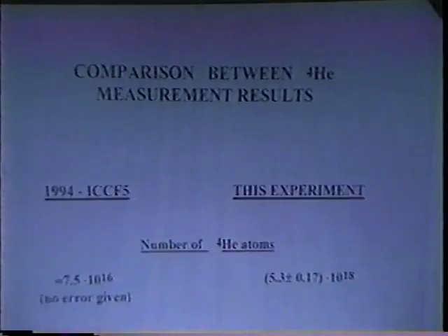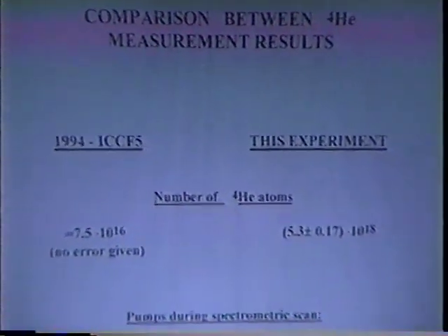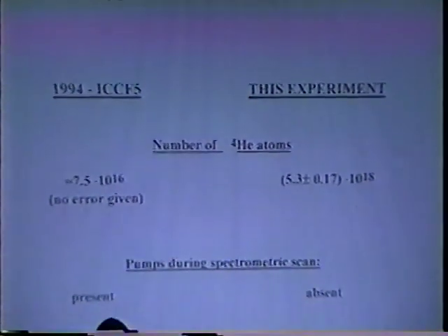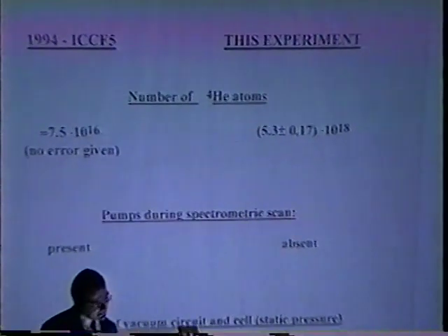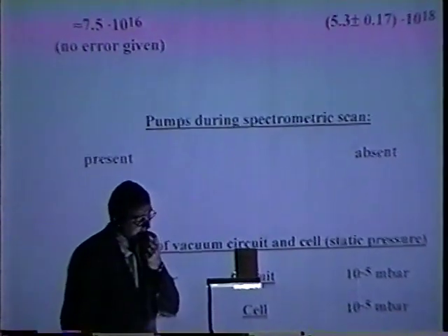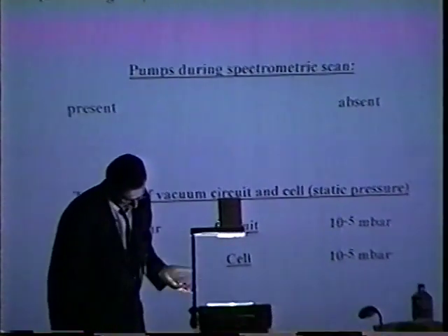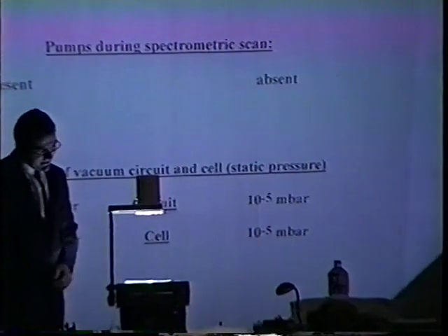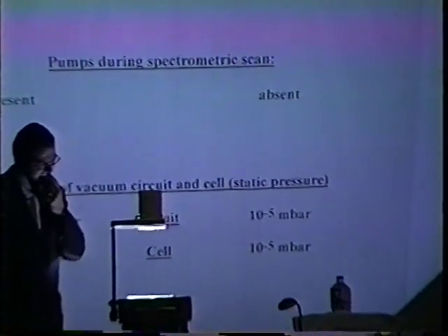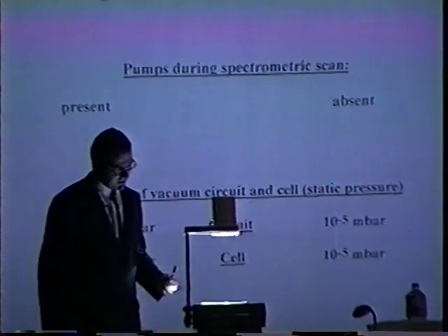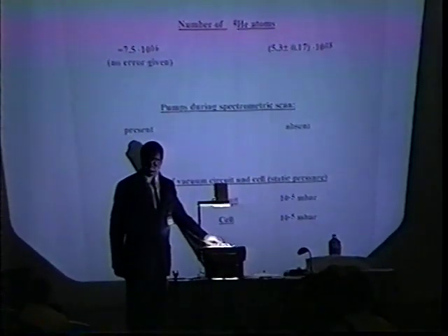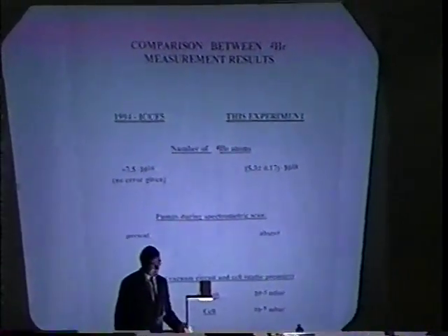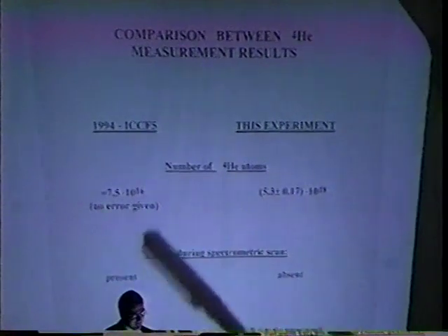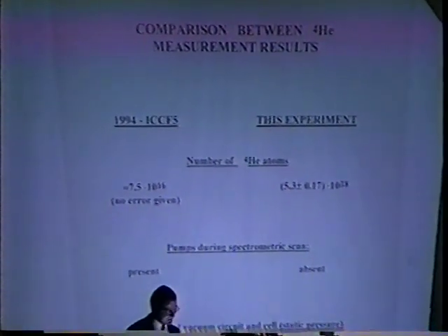These values can be put in comparison with the values shown in ICCF-5 in Monte Carlo, where we obtained 7.5 by 10 to the 16 atoms, while in this case we obtained a number about 100 times larger. The difference between the two measurements was the fact that in the old one, there was a pump present during the measurement, while in this case the measure is completely static. That's also the reason why we didn't give any error about these measurements.